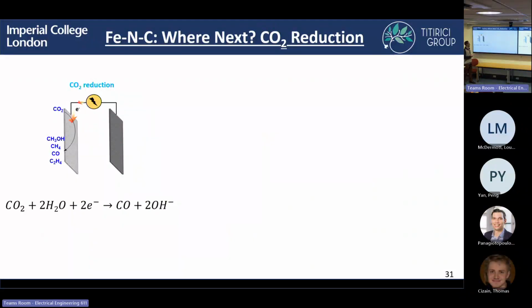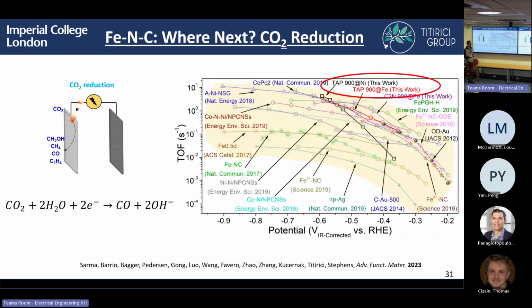And there are also different applications for these iron nitrogen carbon catalysts. Jesus has done a lot of work developing them for CO2 reduction. You can very efficiently make CO from CO2 with these single atom catalysts. In that work, they found that if you use our same catalyst, this TAP 900 with iron, we can achieve in line with state-of-the-art performance compared to silver or gold, which are the commercially used catalysts for CO2 reduction to CO. So there are other applications of these catalysts beyond just oxygen reduction.